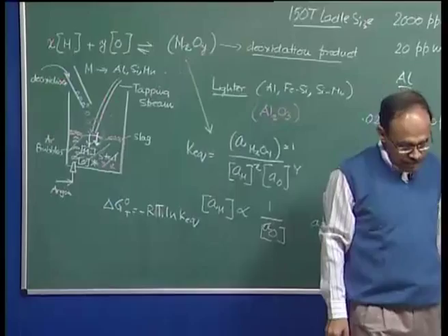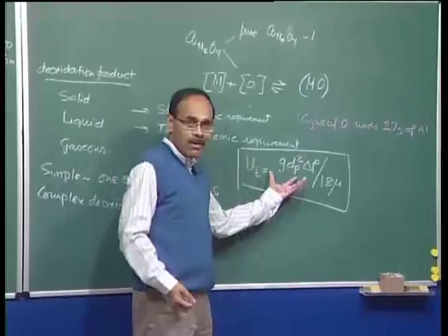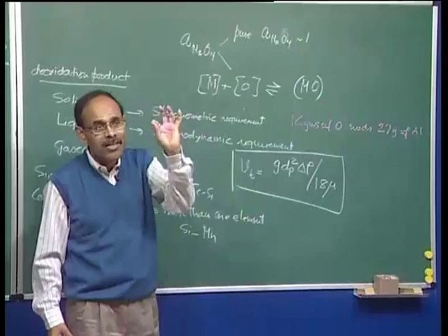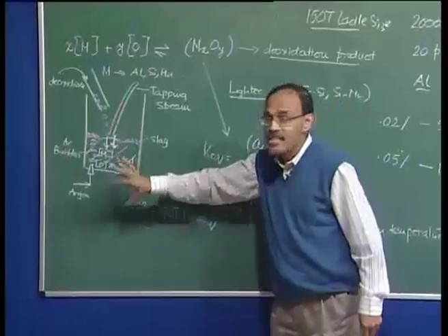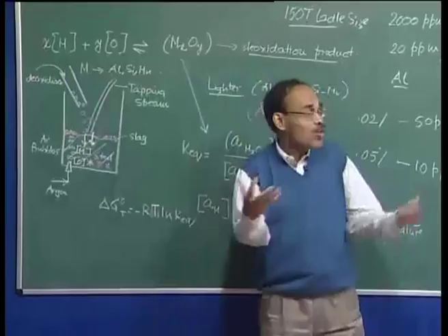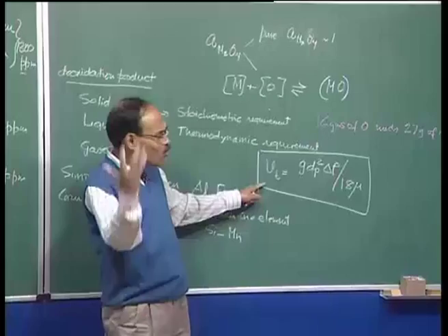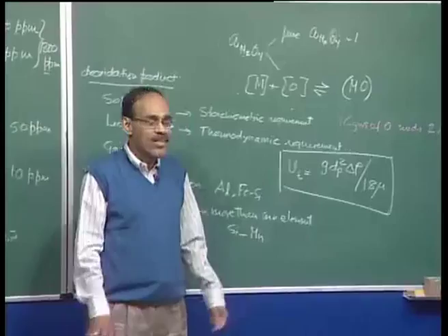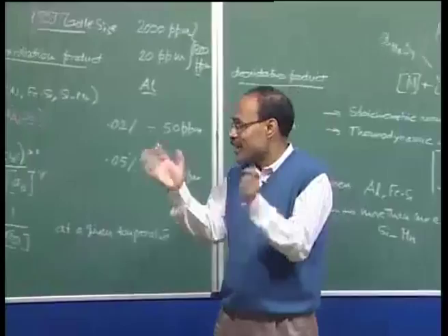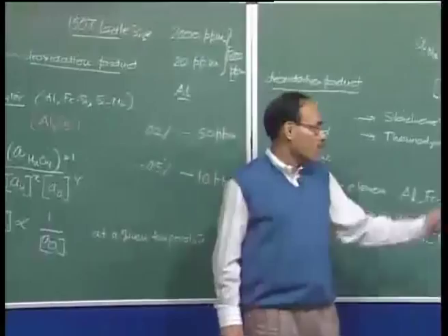where they can get absorbed. Of course, Stokes law is a very simple law, and we all know that it is valid for laminar flow, with Reynolds number of the order of 1, a very weak, quiet flow. In this particular system there is fluid motion also; it is not a particle rising through a stagnant bath. Also, the surface tension in high temperature systems is different, and the particles may completely wet or may not wet. So this is an approximate order of magnitude calculation that need not be taken too seriously. We just get some idea of what size of inclusion can float and what size cannot, and nothing beyond that. No serious process design calculations or inferences should be drawn on the basis of Stokes law as far as inclusion flotation is concerned.